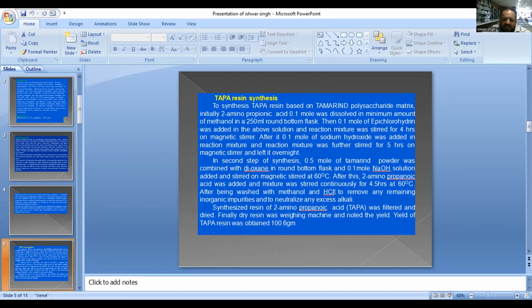In the second step of my synthesis, I took 0.5 mole of tamarind powder, the natural polysaccharide, which is used as a matrix. To make the mixture basic, I again took 0.1 mole NaOH solution and added it at 60 degrees. After this, I added 2-aminopropanoic acid, and finally washed with methanol and acid to remove the extra impurities. Finally, I synthesized the 2-aminopropanoic acid resin, filtered and dried it.